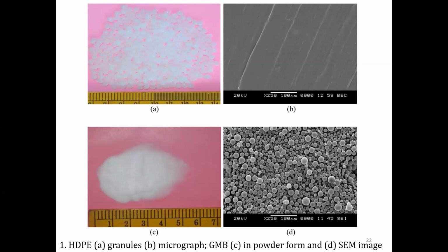You can see a smooth texture of HDP in figure 1B. We took a micrograph of that. Glass microballoons are readily available because these are artificially made. Please do remember, when we say microballoons, these are hollow microballoons. What you see in 1C has an outside diameter of 15 microns, as small as that, with a density of 0.6 gram per centimeter cube, and a wall thickness of only 1.5 microns.